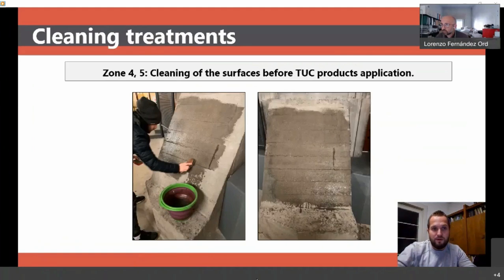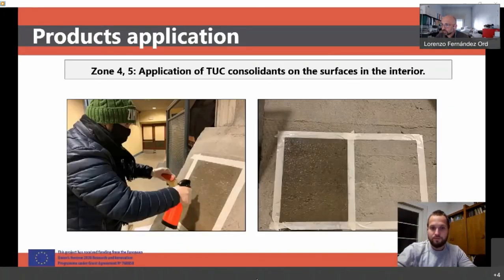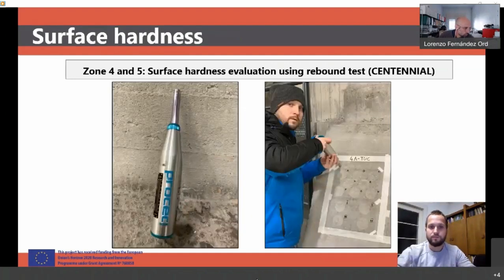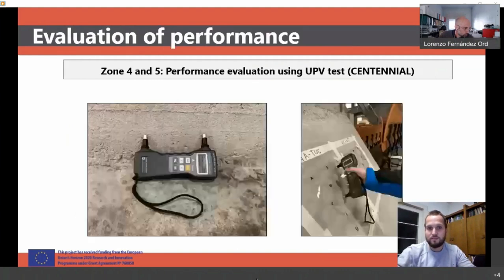And in zone number 4 and 5, where similar products, consolidants, were applied, we performed cleaning by means of the same procedure. And after 1 week, we applied the products, one layer and two layers of TUC consolidants, and checked the performance with the rebound test, with the ultrasonic pulse velocity test.